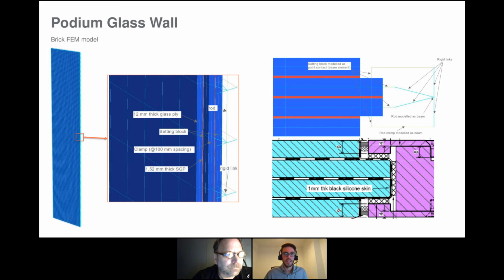We were quite refined in terms of the various components that we have to model. And as you can see, probably better in the section cut on the right, where we compare a section through the finite element model and the section detail for the rod to glass clamp, we had to reproduce as accurately as possible the behavior. So we had to introduce clearly not only the glass and SGP interlayer in the model, but also the point contact, so the bearing point between the glass and the clamp, and carefully the rods and all the linking between these elements, the clamping, and the bearing block. So they were quite accurate models, which also take quite a long time to run.